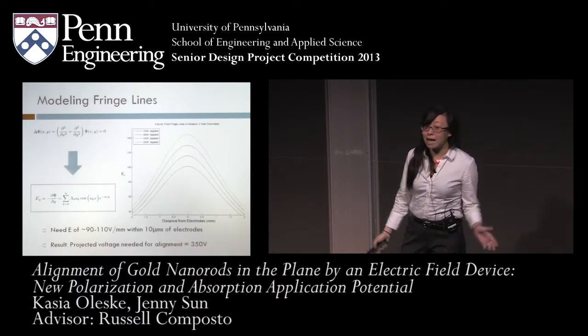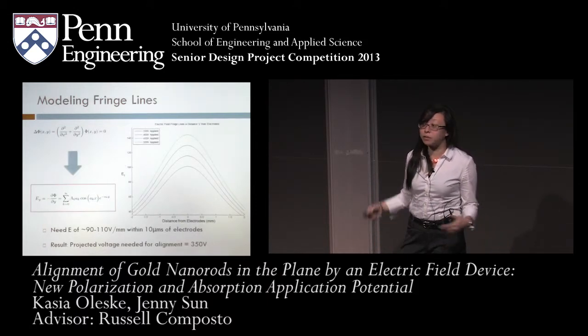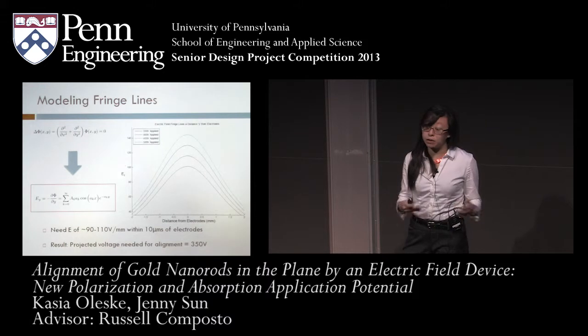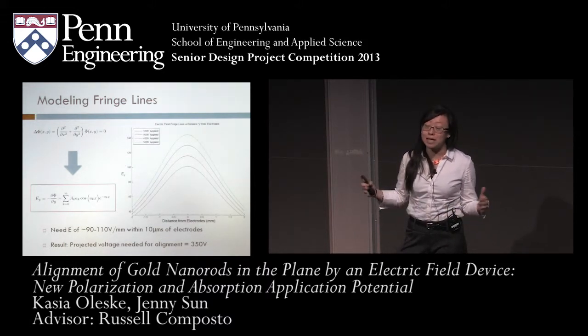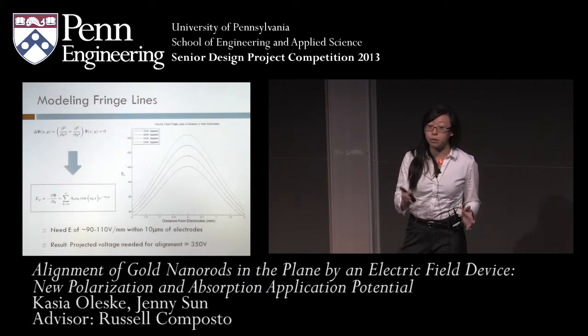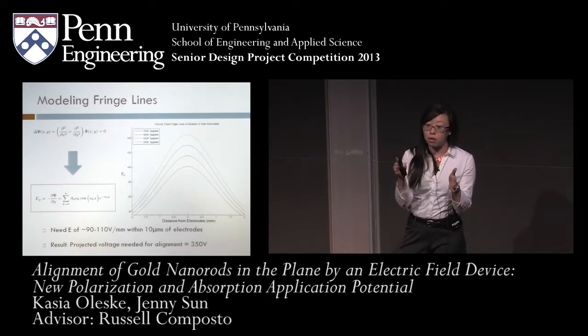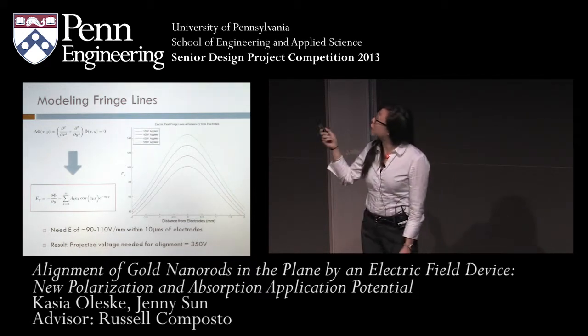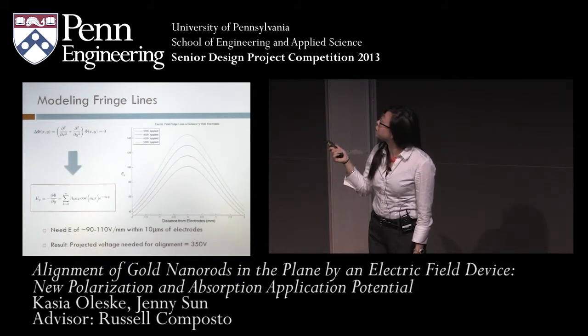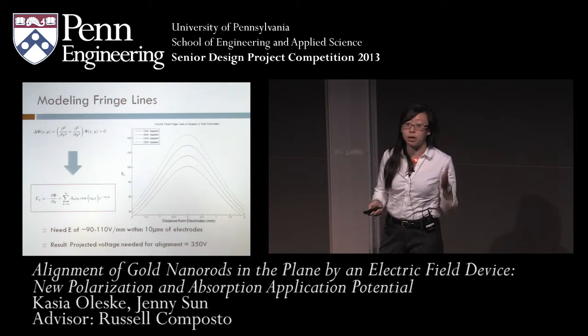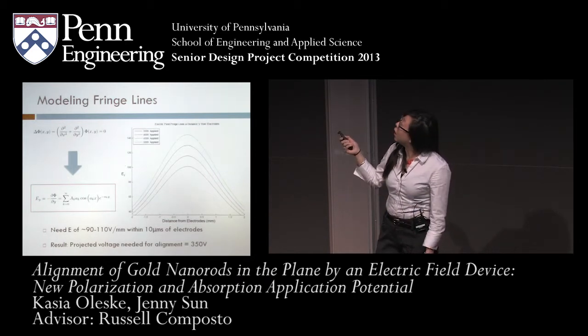And so in order to actually design our electric field device, we first needed to model the fringe lines coming out of our electric field. This is because we're actually aligning by the fringe lines of an electric field. We're not putting it through, we were running our samples through the fringe lines. And so in order to model that, we had to solve the two-dimensional Laplace equation, which yielded the electric field in the y direction beneath our electric field. And so here's a model of a couple of those fringe lines right here.